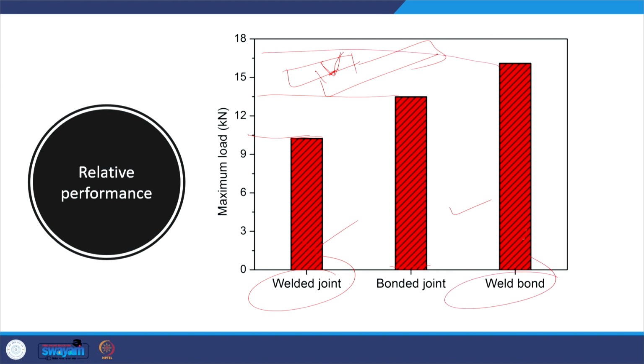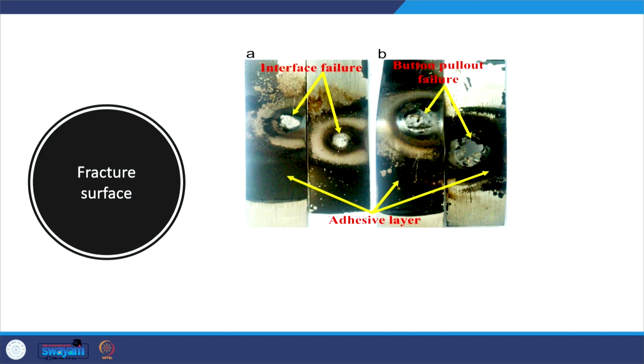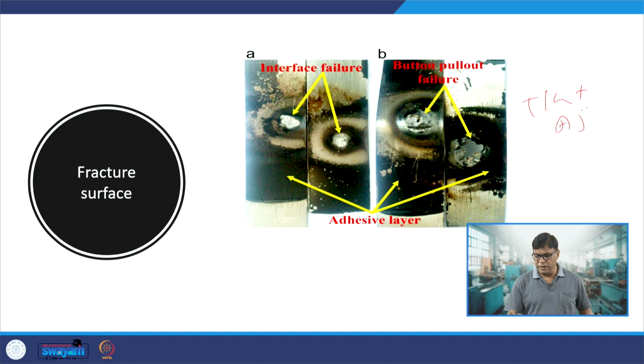So, weld bonds where TIG welding is clubbed with adhesive joining improves the load carrying capacity significantly. This is attributed to the improved load distribution over the larger bonded area between the two sheets which are being joined. In the TIG adhesive joint, when the load is applied, the failure can occur from the interface.